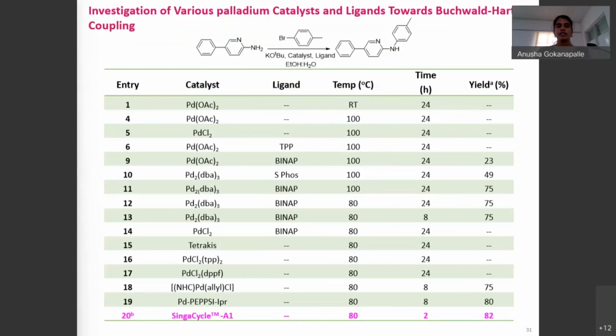Next is investigation of various palladium catalysts and ligands towards Buchwald-Hartwig coupling reaction. In a similar way, 2-amino-5-aryl substituted pyridine was taken as a model reaction. We started the reaction with palladium acetate without addition of ligand, and we did not observe any yield. Next, we added ligands to the catalyst and observed somewhat of an improvement in yield. Next, we switched to palladium NHC catalyst.